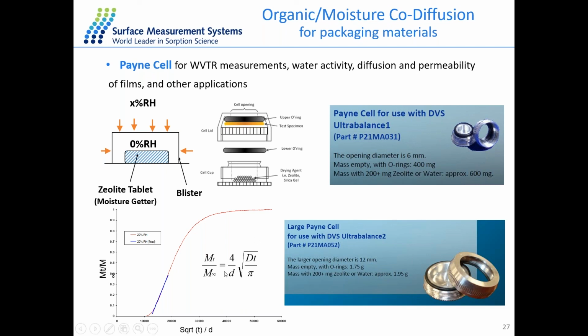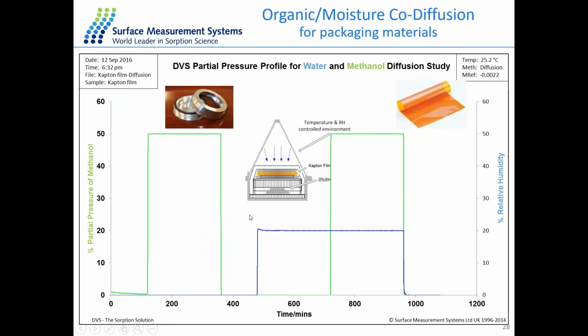So according to Fick's law, we have the thickness of the film sample, and we have the mass at equilibrium, and we do the fitting for different humidities, and then we can get the diffusion coefficient of the film sample at certain humidity. And from the slope, we can also calculate the permeability of this thin film sample. So the case study here is a diffusion study. Actually, it's a co-diffusion study for the packaging material.